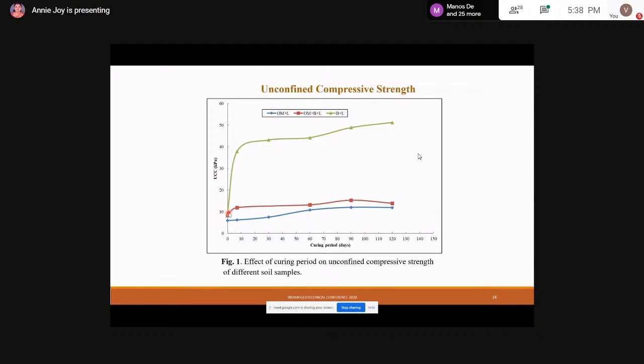Here you could see that the green curve represents bentonite plus lime soil mixture. It is very clear that as the curing period increases, the UCS strength increases in the case of bentonite lime soil mixture. But when you observe this red curve, which represents organic matter plus bentonite plus lime, initially there is a slight increase in strength up to 90 days, after which it goes on decreasing. And when you compare it with the strength of bentonite and lime, you could see a decrease of about 73%.